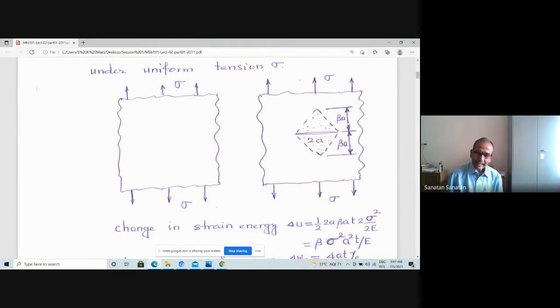And therefore, what he said is that this shadow area does not have any energy. Energy means when you load a component, it has strain energy per unit volume. But some bit of material becomes load free, and therefore it does not have any energy content. As the load increases, the crack extends, the size of this shadow region increases, and the quantum of material that becomes energy free also increases. So crack extension has two effects. It increases the shadow area, so the material that is losing energy increases. And simultaneously, as the crack extends, the surface of the crack increases, and it requires more energy for creation of new surface.